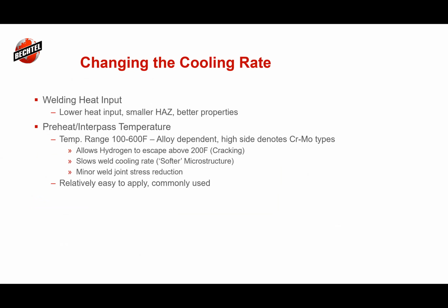Sometimes it's better to have a moderate or even a higher heat input, without obviously exceeding the welding procedure and what you can achieve with the material. But the heat input, having mins and maxes, it's also the preheat interpass temperature.